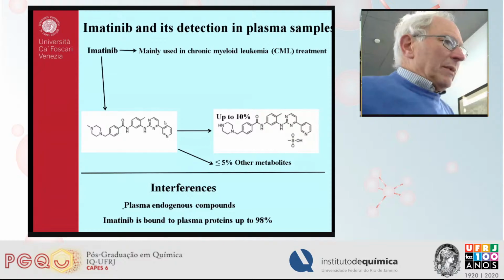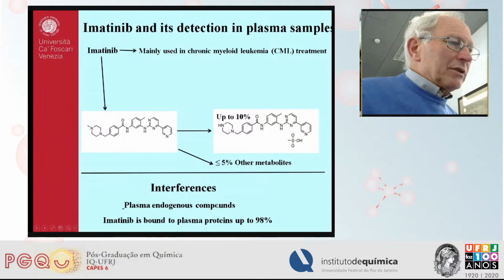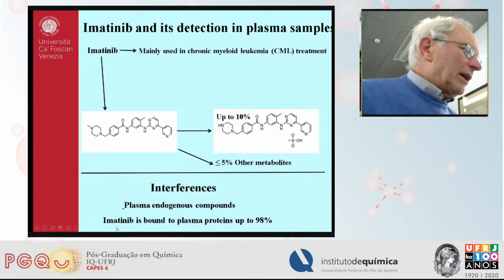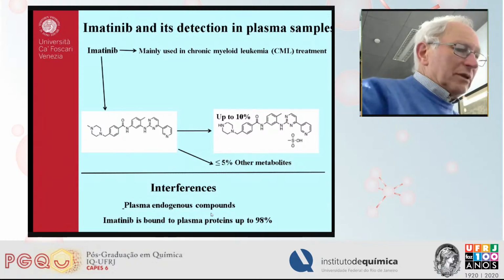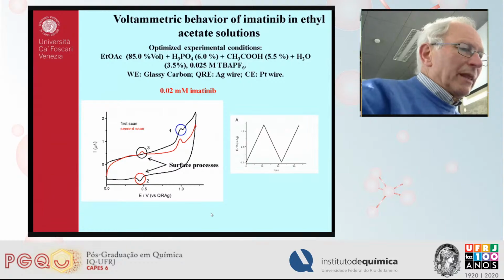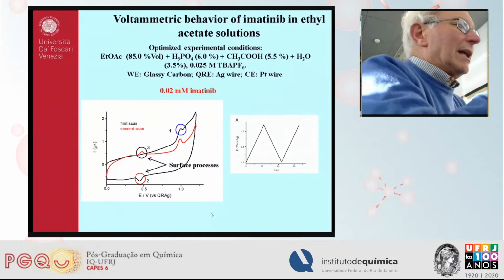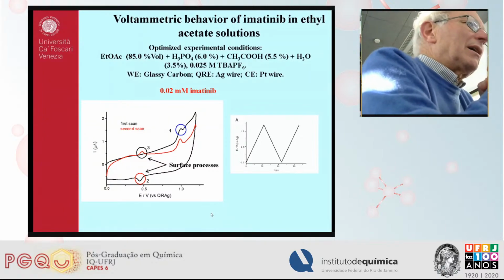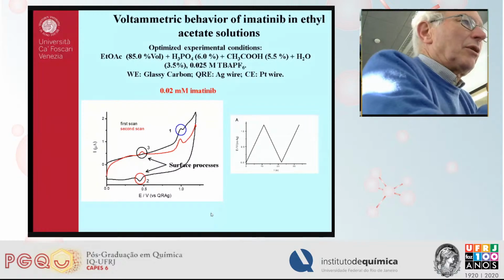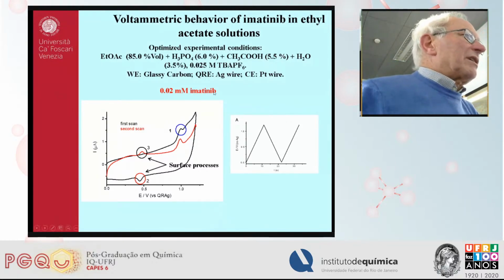The interferences may be due to the plasma endogenous compounds, as I said before for irinotecan, and also to the fact that imatinib is bound to plasma proteins up to about 98%. So it's strongly bound to plasma protein. In this case, in order to get good results, we changed a little bit the voltammetric techniques employed, but also the solvent. The best solvent that provided good results was ethyl acetate in a solution containing strong acids, again using a glassy carbon electrode.